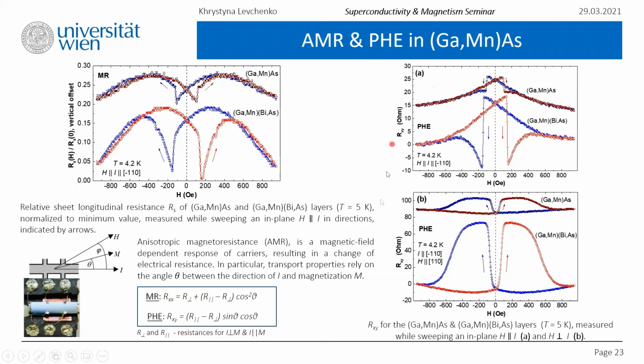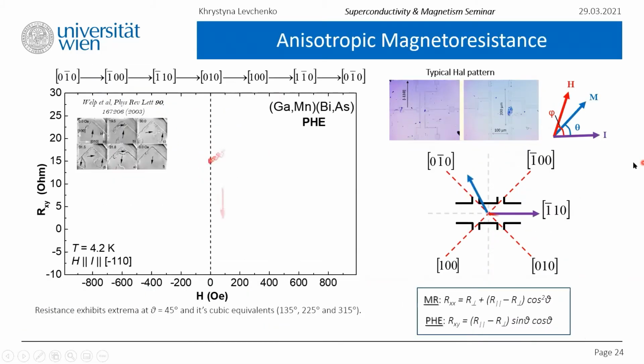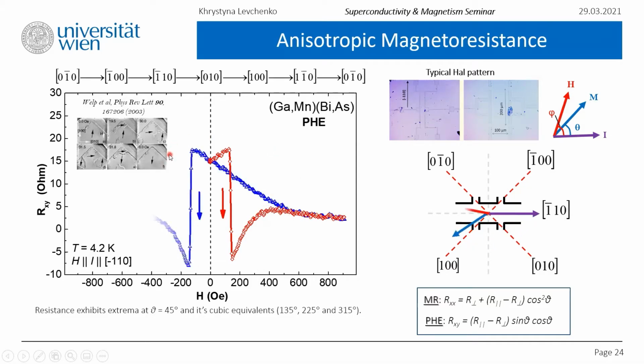The difference in here, for example, this is a longitudinal component, this is a transverse component. The difference in here being that the field and current are both applied along the -110 direction, while here the current is along -110 and field is along a harder magnetization axis, being 110. So let us see how the measurement is proceeding in more detail, and especially in the area of our interest between the recurrence points, on the example of the planar Hall effect.